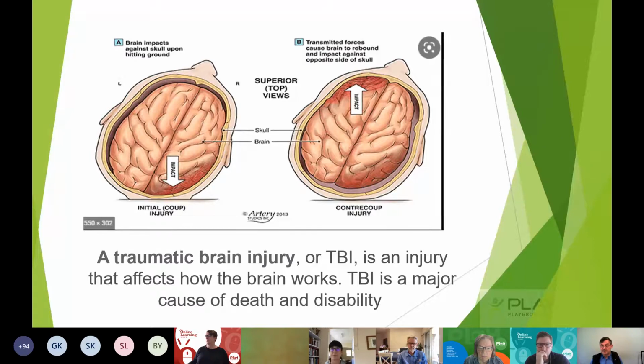This means if you fall from a playground, will the surface catch me? Is it soft enough? One of the things I see all the time is people walk into a playground area, and they jam their foot up and down and they go, yeah, this is nice and soft. It'll be okay. It'll pass. Now, I've been doing it since '93 and I can't tell. You can have a soft surface that is only 20 mil thick with concrete underneath it, and it feels okay with your foot when you walk into it.